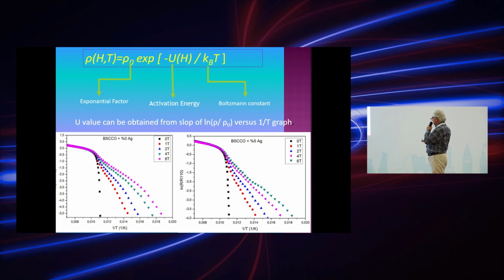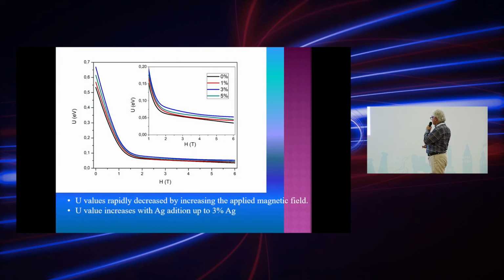From this graph, we have deduced the activation energy. Okay, activation energy calculated, and you can have a look. The best one is again 3% of silver, and the U value rapidly decreases by increasing applied magnetic field, and the U value also increases with silver addition up to 3% of silver.